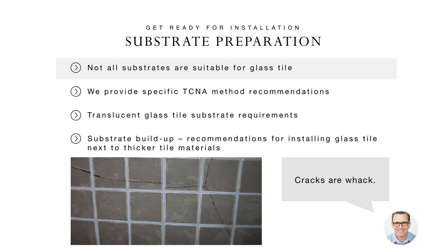And you can see here from this photo, this was a single float mortar bed where the entire substrate started to move and flex and it cracked through the tile. This may or may not have been a problem with the porcelain, but it was a very obvious problem with a glass tile. So that's first and foremost to keep in mind.